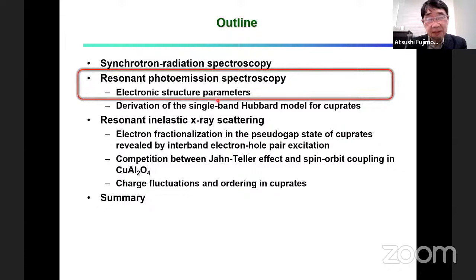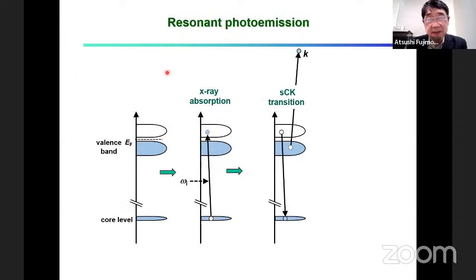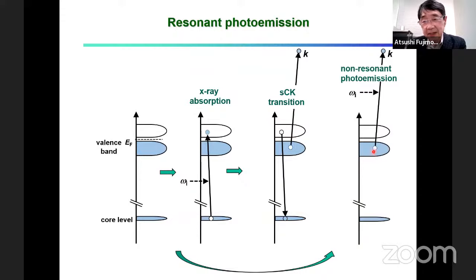And first, let me start from my old work. Resonant photoemission started many decades ago. It is photoemission followed by X-ray absorption from the core level to an empty valence state, and then the so-called super Coster-Kronig transition. The excited electron is combined with a core hole and then kicks out valence electrons. This final state is identical to a direct non-resonant photoemission. So two final states interfere quantum mechanically and show a so-called Fano resonance, and photoemission intensity is dramatically enhanced.